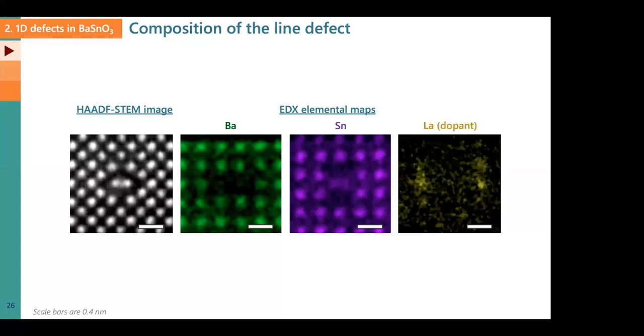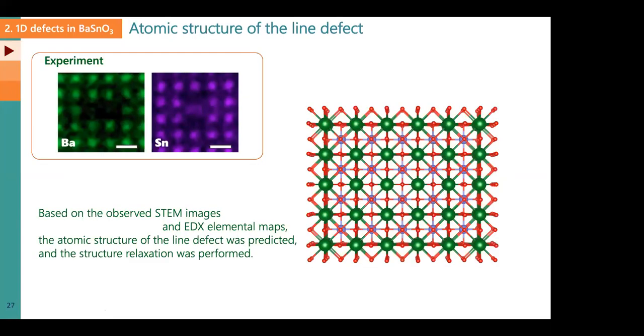This material also has some dopants in it, some point defects, and it looks like they're sitting in a particular spot, right next to this line defect we discovered. This is going to play a role in our story, but it's cool that we can even see individual point defects around our line defect. If you look at the tin image, you can see that the pair in the middle are indeed tin atoms. They are not barium, but tin. You can see the signal there. That was kind of exciting.